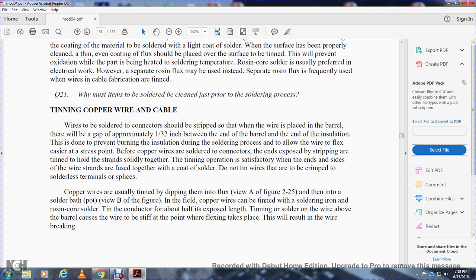Copper wires are usually tinned by dipping in flux, view A, figure 2-25, and then in a solder bath pot, view B of the figure. Small copper wires may also be tinned with a soldering iron and rosin core solder. The tin over the conductor is about half its exposed length. Tin and solder over the wire above the barrel cause the wire to be stiff, and at the point where flexing takes place, this will result in the wire breaking.